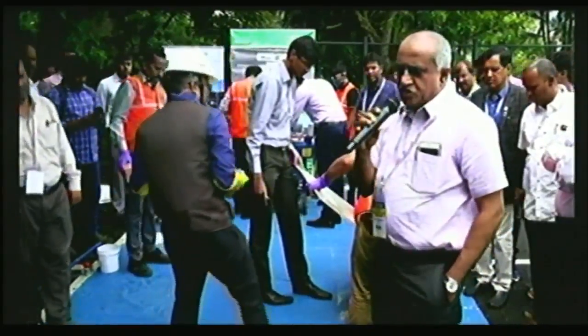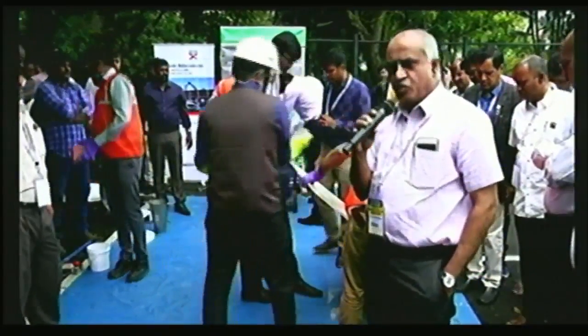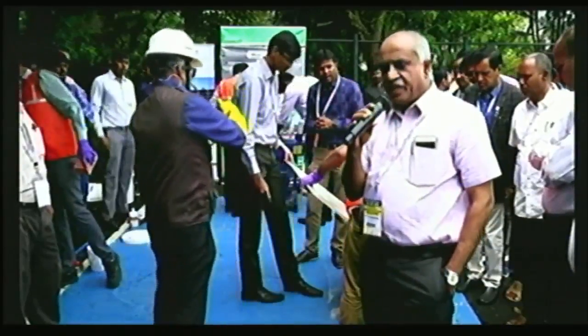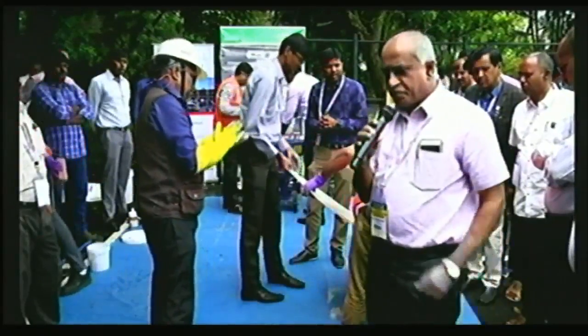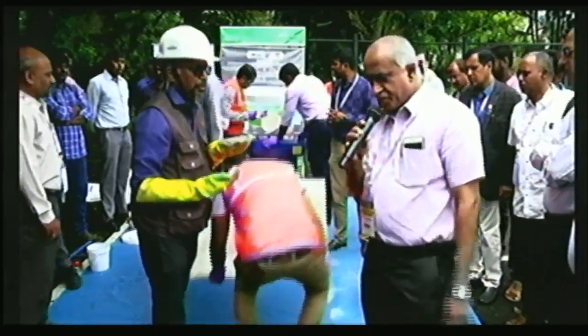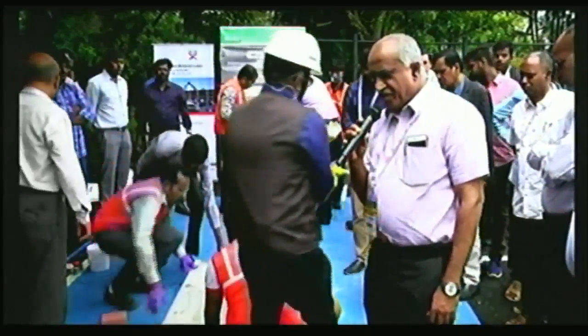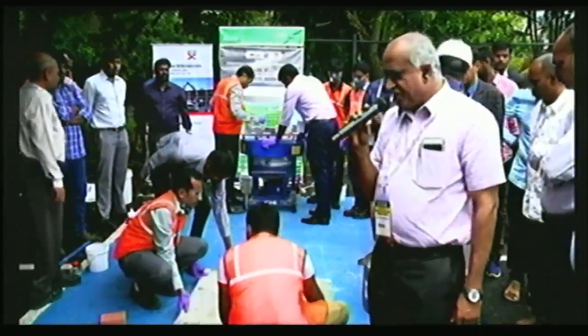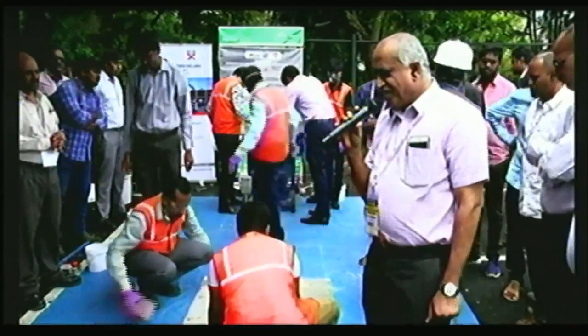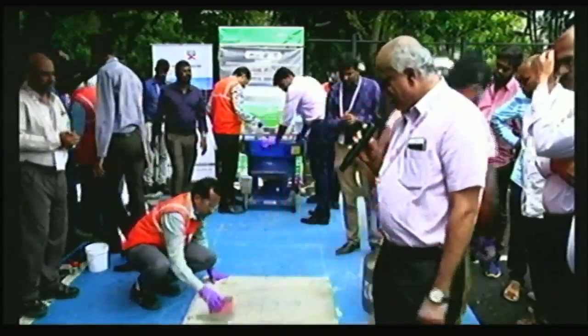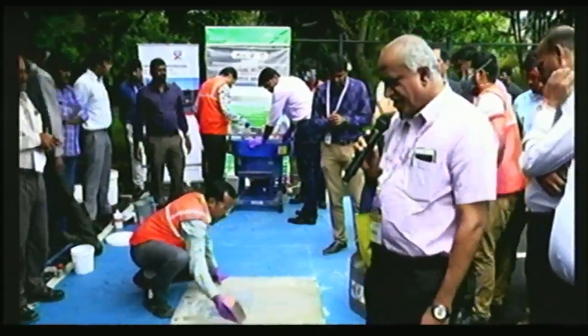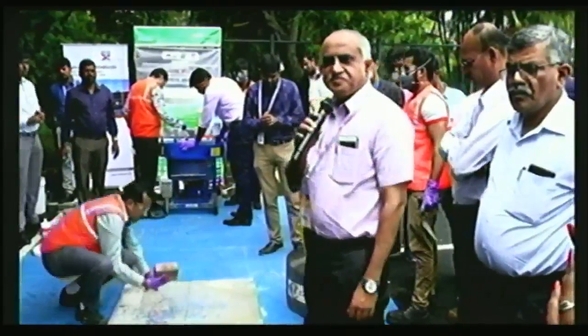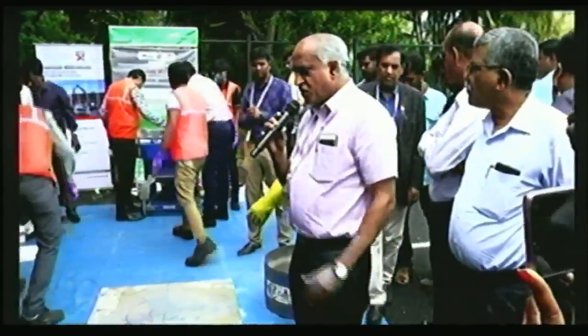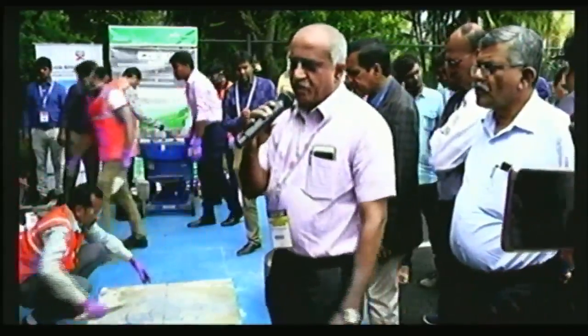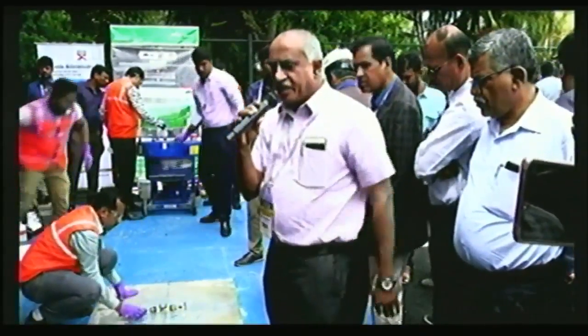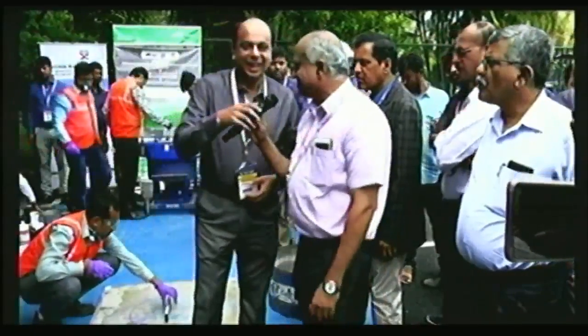Irrespective of the zones, that is zone 2, zone 3, and zone 1, have you kept the fine aggregate or total aggregate proportion the same? I think they are the same. Just looking at the mix. See what we did in the laboratory: 991 we used for zone 1 and 928 for the other. As the zone increases from 1 to 2 to 3, you reduce the sand content. Yeah, zone 3 we have reduced. We are at 879 against the 991.